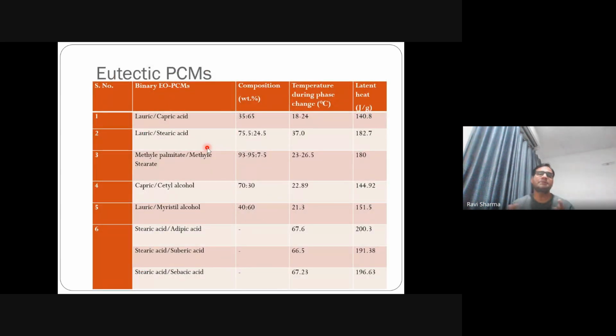Then the PCMs can also be prepared as a eutectic. We can mix two or three PCMs and come up with one single material. So we do that in order to tailor their melting point. For example, I have two materials which are available in two different melting temperatures. One is at 40 degrees centigrade, another is at 45 degrees centigrade. But my application requires a material which should have a melting temperature of 42 degrees centigrade or maybe 42.5 degrees centigrade. Very peculiar temperature, but I don't have a material available.